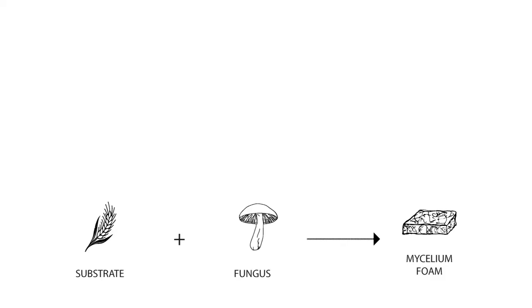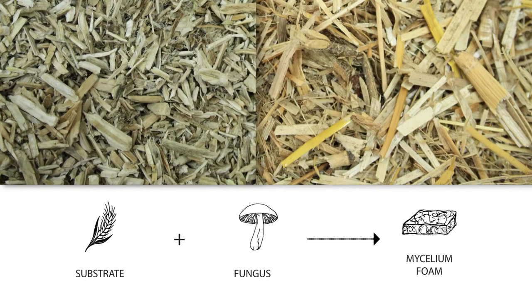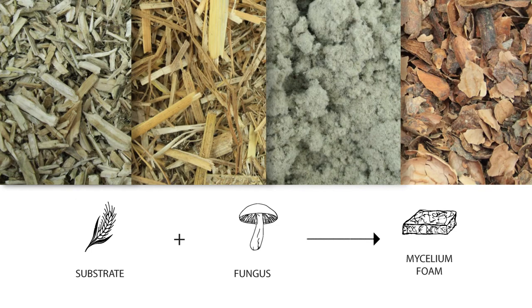The growing pattern and filamentous structure of mycelium are of particular interest to us, since they allow the living organism to be used for the production of biobased materials. In fact, mycelium can bind different natural substrates, for instance hemp, straw, cellulose and cacao, and many others, to form a mycelium-based biocomposite. A biocomposite is a composed material consisting of a fiber and a binder. In the case of mycelium composite, the fiber is called substrate and the binder is the mycelium, which acts as a glue holding the particles together.